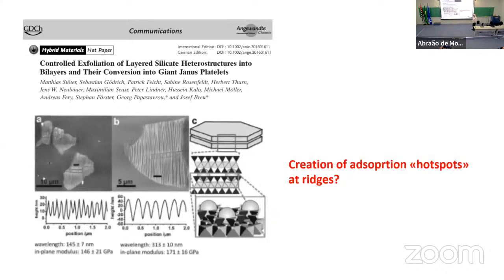Another issue that we are looking into is not mixing it with graphene, but just the clay layers themselves. This is an experiment that was done by our collaborators in Germany. They take a clay layer, they put it on a flexible substrate. It is stretched when they put it down. They put the clay on top, they release the stress, and then the clay wrinkles. And this actually shows how easy it is to wrinkle these clay sheets.